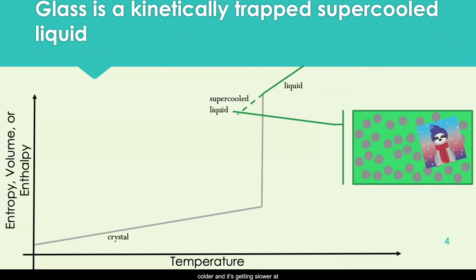At some point, it becomes so slow that the system can't keep up with the fact that I'm still cooling it, and it gets sort of stuck a step behind. It gets kinetically trapped in the glassy state. This is how we define a glass. But if you were listening closely and thinking carefully, you might say, it's not a great definition, since if I change my cooling rate, my glass will change.